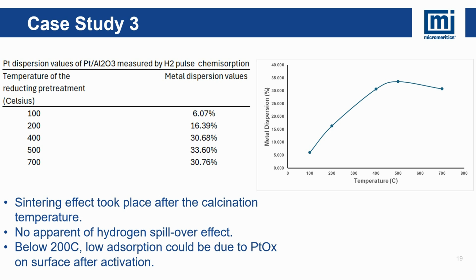Beyond this temperature, the dispersion value began to drop, indicating the onset of sintering. As mentioned earlier, when sufficient energy is provided to platinum particles, they begin to vibrate and migrate, forming larger clusters, which leads to a loss of catalytic activity. Lastly, no hydrogen spillover effect was observed in our experiments.